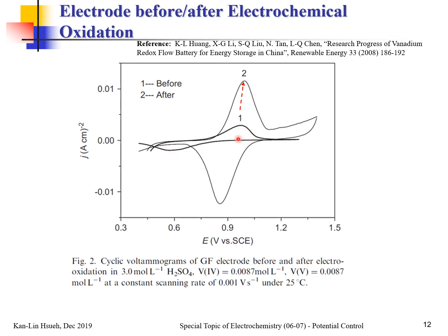Before, the graphite electrode was less active, so you may treat it as an irreversible reaction. But when you roughen the electrode surface, for example by sanding it with sandpaper, the surface area increases and it becomes more active. The peak current increased, and the difference between the peak potentials is getting closer.